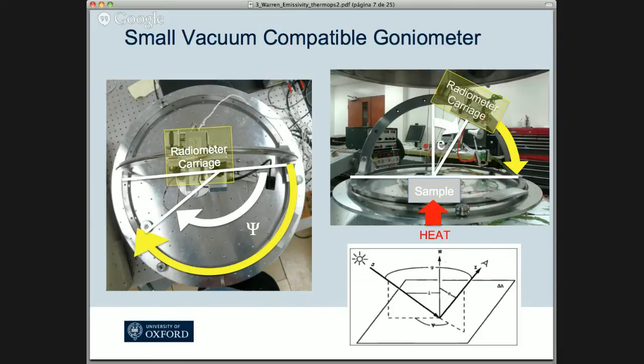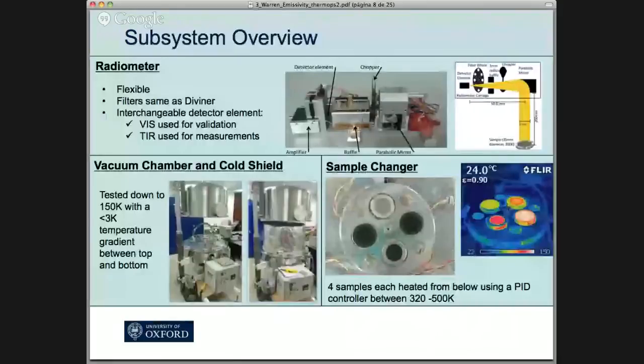So this is just some additional details about the goniometer. The radiometer, we built it to be very flexible, so we can change the detector elements and baffles and filters depending on what we want to do. If we want to make measurements in the visible, we can do that by putting in an appropriate detector element and filters. Or if we want to make measurements in the thermal infrared, again, we can do that by changing out the detector element. The filters we are using are not coincidentally very similar to the filters on Diviner.